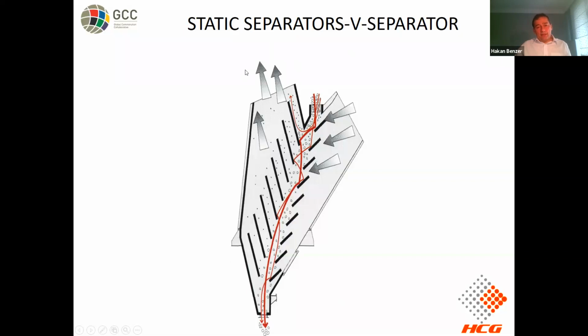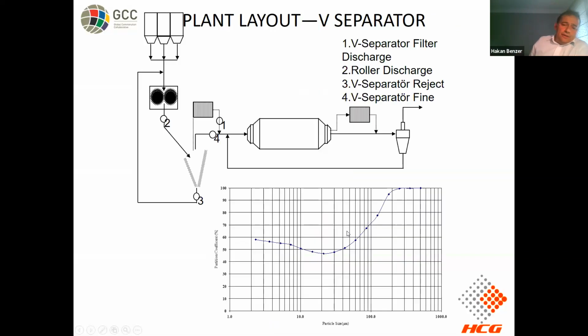In a typical cement application, we can expect to receive a P80 value of 200 microns from the fine section of a V classifier running with an HPGR. If we look at data from the industry, this is the performance curve of the V separator. Because of the high circulating load, the efficiency seems to be lowered. The bypass value is 50%. This means that the circulating load ratio is quite high, which provides a very steep size distribution at that point.